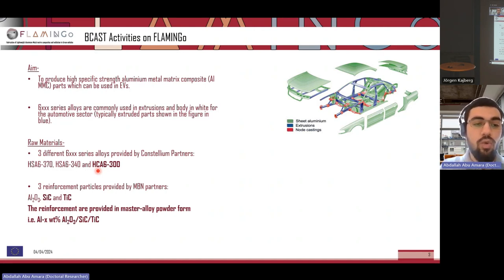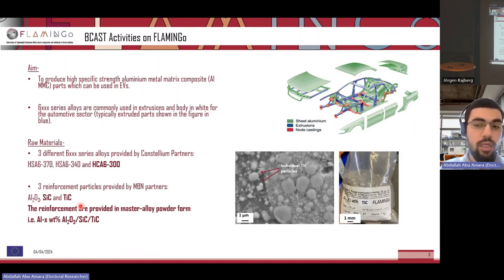As for the reinforcement particles, which were provided by MBN, we were provided with 3 different types of particles. So alumina, aluminium oxide, Al2O3, silicon carbide, and titanium carbide. And the reinforcements are provided to us in the form of master alloys, as Alvis already mentioned. So the master alloy essentially is an aluminium X weight % either alumina, silicon carbide, or titanium carbide. So here we can see the microstructure. These are titanium carbide particles, and you can see the matrix in the background is aluminium.